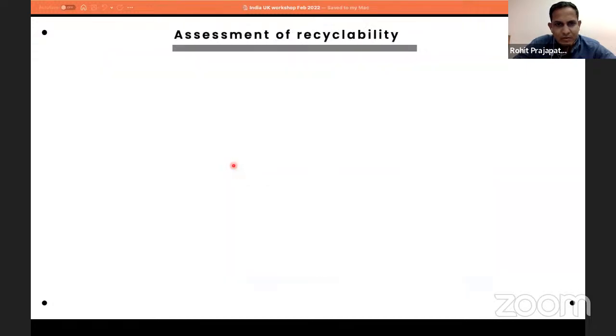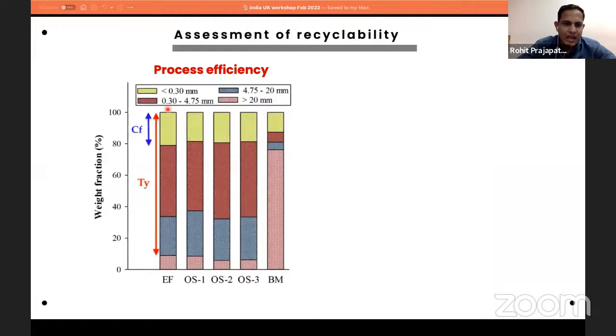So the assessment of recyclability was done in the similar way. So we have the process efficiency. So again, you have this first box where EF, electrical furnace, and then OS are the trials from the solar heating. So you can see that it yields almost comparable products. And just to highlight the effect of heating, you have this last trial, BM, which is just ball milling. So if you don't heat the concrete, then your yield is very less. And then aggregates, what you produce will not be free from the dead mortar.